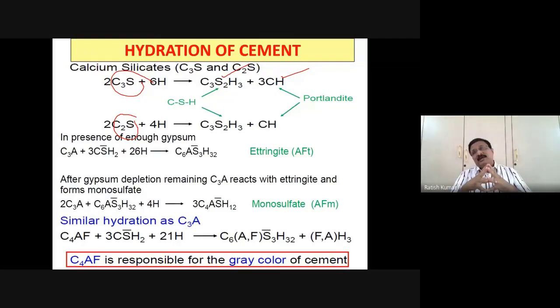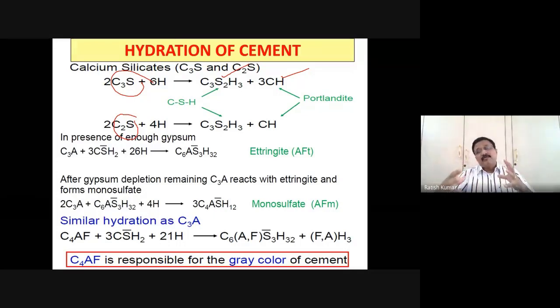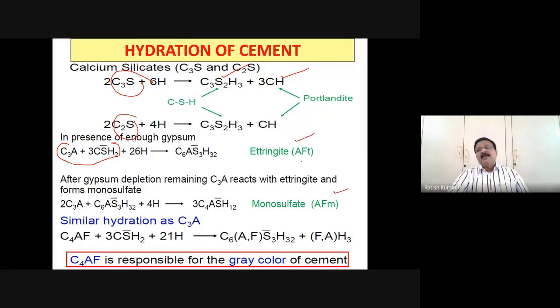But the point here is, are we really able to get a good advantage from the carbon dioxide point of view? That is a question which we try to point out. The other thing is the combination of tricalcium aluminate with water producing your AFt as well as AFm phases. AFt phase is nothing but ettringite, which you can identify by the needle-like crystals, and that is going to take some time and then convert from the ettringite part to the monosulfate part.